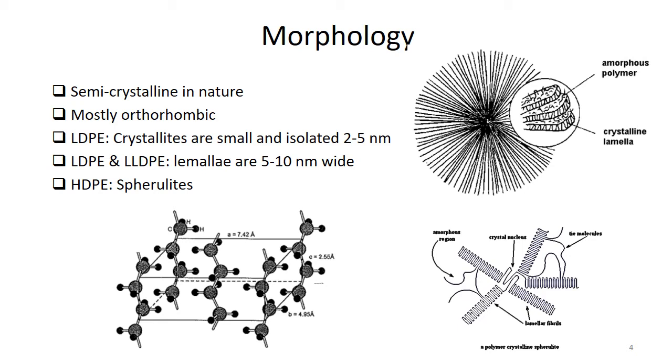At the highest level of crystallinity, exhibited by high density polyethylene, crystalline lamellae range from 10 to 20 nanometers in thickness with lateral dimensions of up to several hundred nanometers. It means they grow to such big sizes. Lamellae are typically parallel with their neighbors, and spherulites are well organized with diameters up to several tens of micrometers.